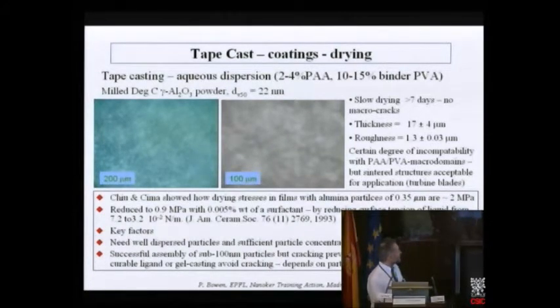You can modify interfacial tension by reducing it from like 72 to 32. Chiu & Cima showed that they can reduce below the 2 megapascal down to 0.9 megapascal with just the use of surfactant. It really depends on your system, depends on your size. You can modify these things. These are the things you can play with: surface tension, particle size, and use of additives.